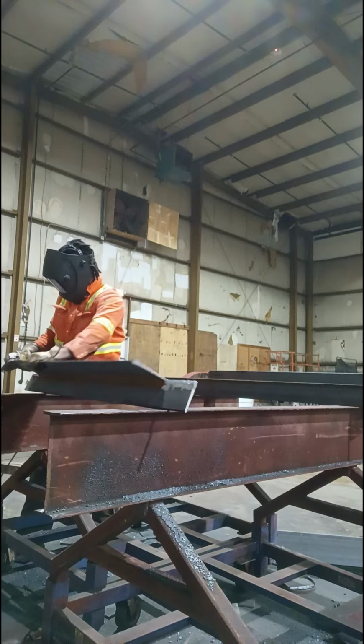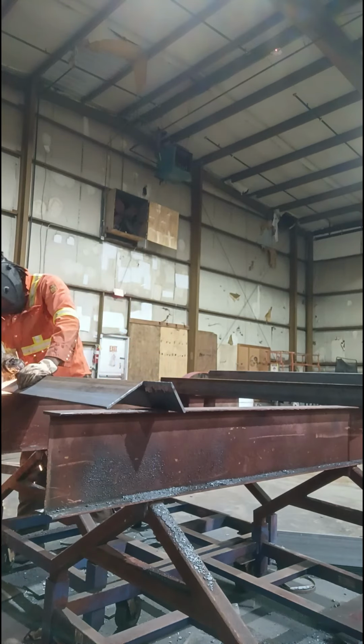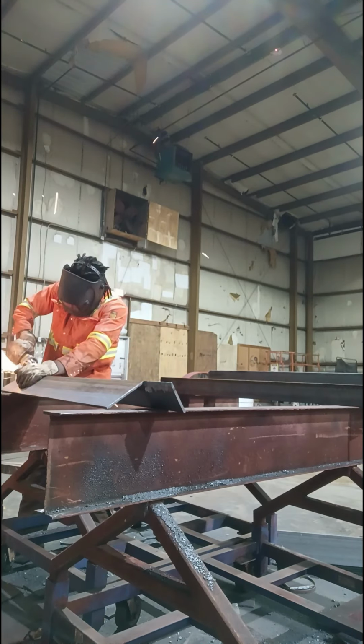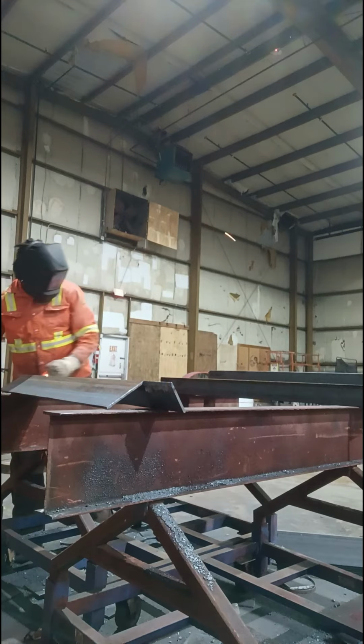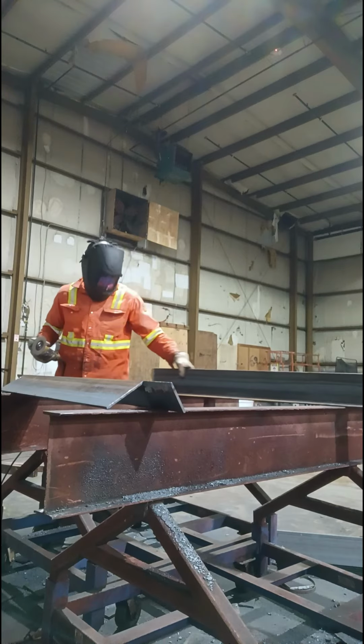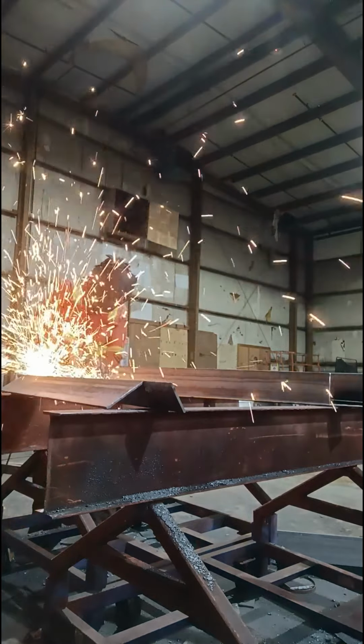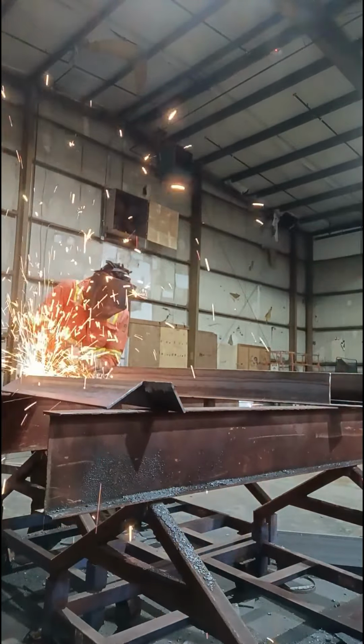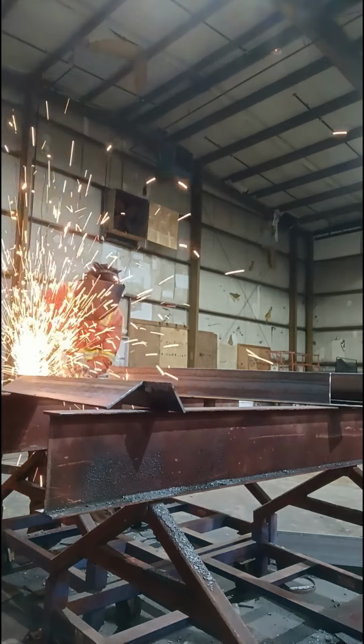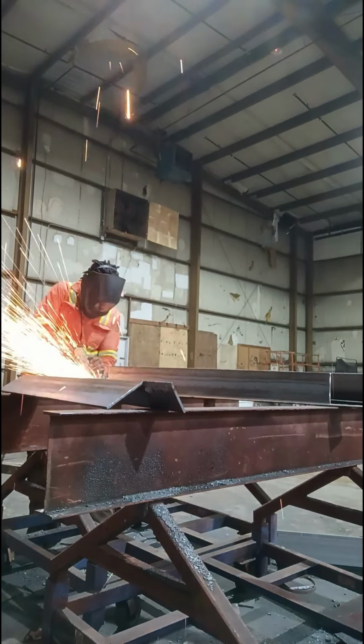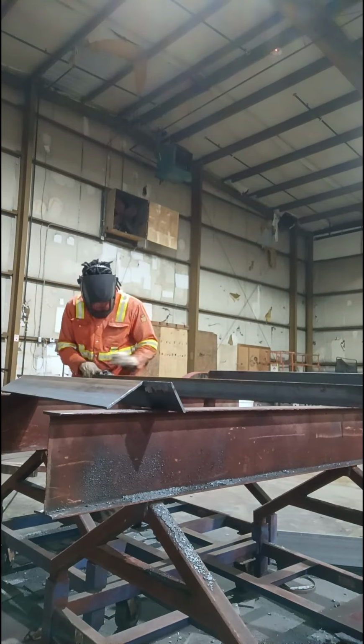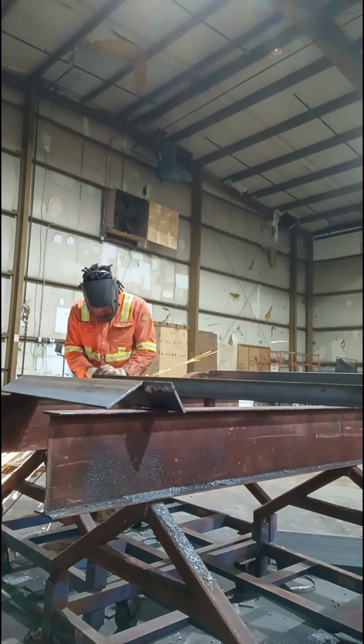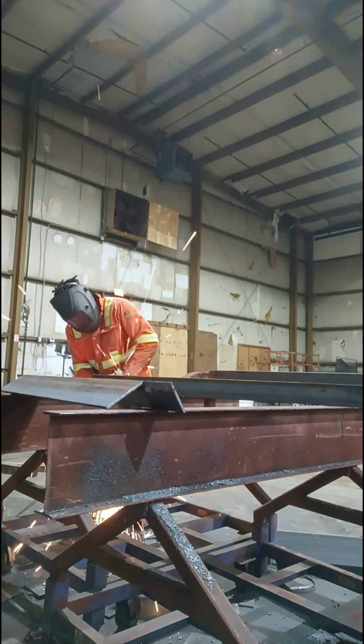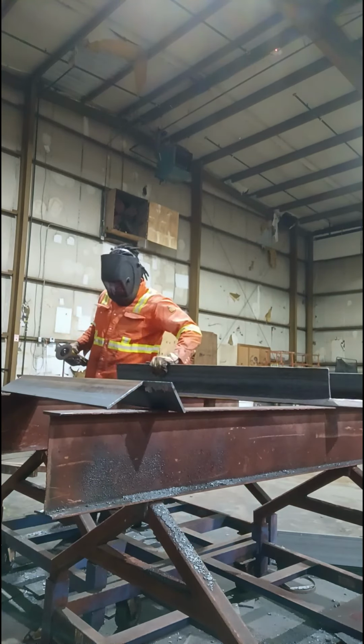Welder technique is another layer in the system. Incorrect travel speed, poor torch or electrode angle, inconsistent arc length, and improper manipulation all affect weld quality. Even skilled welders will struggle if conditions are poor or preparation is inadequate. Consumables are often overlooked. Incorrect filler material, contaminated electrodes, damp rods, or incompatible wire types can introduce defects that aren't visible until failure occurs.